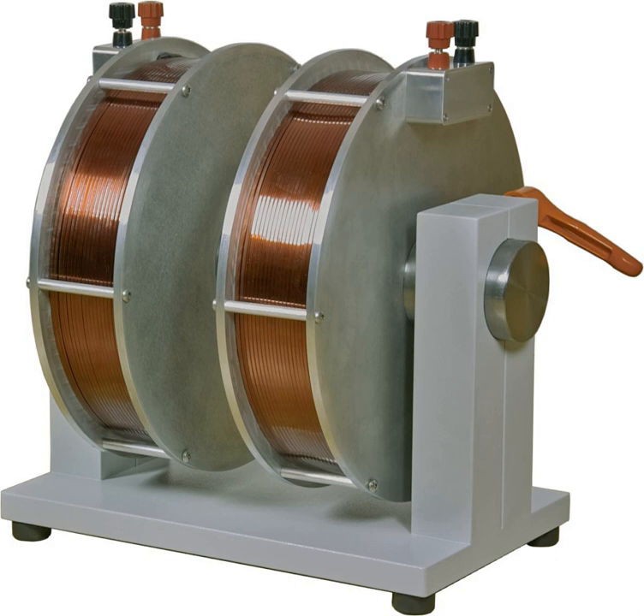To prevent them, the cores of AC electromagnets are made of stacks of thin steel sheets, or laminations, oriented parallel to the magnetic field, with an insulating coating on the surface. The insulation layers prevent eddy currents from flowing between the sheets. Any remaining eddy currents must flow within the cross-section of each individual lamination, which reduces losses greatly. Another alternative is to use a ferrite core, which is a nonconductor.